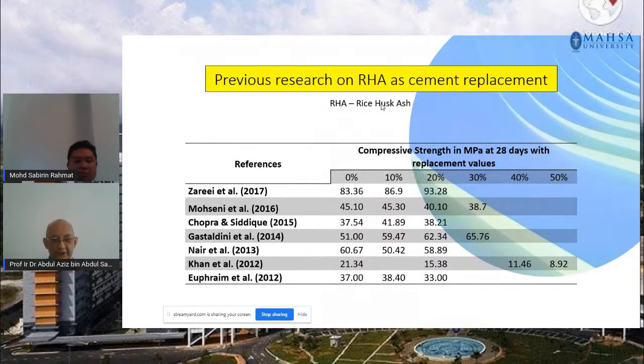Now, in terms of past research on rice-husk ash as cement replacement, again, as you can see, I've listed down a few researchers, and they've also done various percentages of cement replacement with rice-husk ash, from 10% up to 50%. And again, the same approach applies. I was looking for the nearest results that we can observe from their past research, and as we can see, a percentage of between 10 to 20% seems to give the most acceptable concrete strength when you replace cement with rice-husk ash.